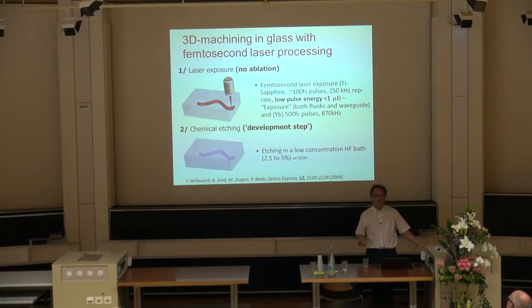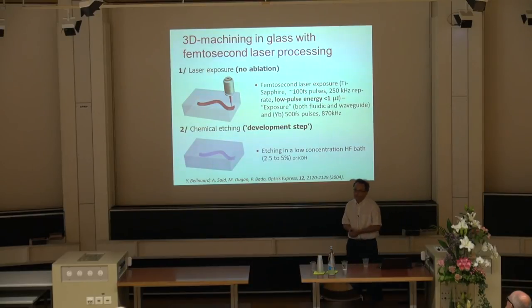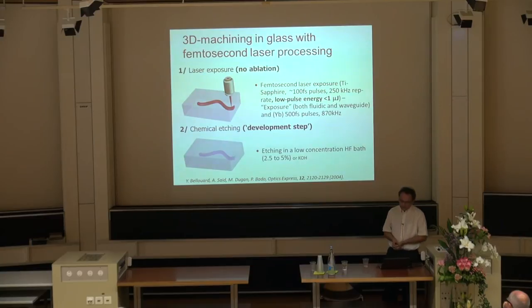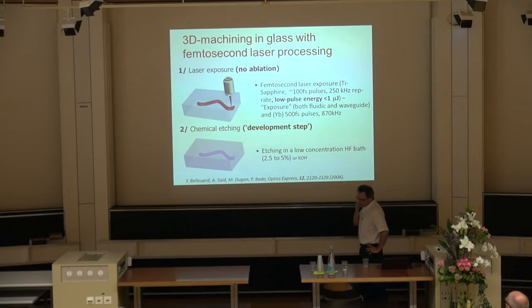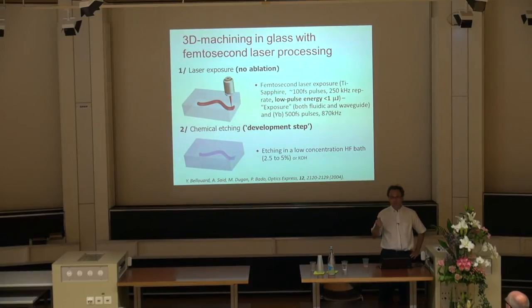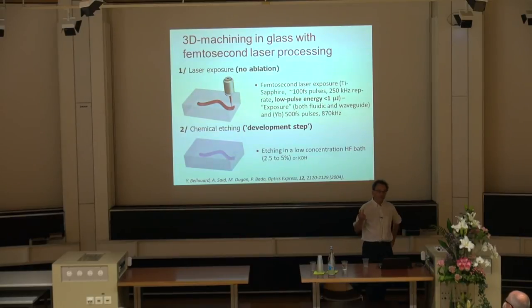Okay, now, how it works. It does sound complicated, but in fact, it's quite simple. We use femtosecond lasers that are actually tabletop. I will show you at the end a picture of the lab, so you will have an idea of how big that is. And what we first do is expose the glass within the volume to the laser beam. And this is done without ablation, so nothing is removed from the material. Okay, that's a very important point. We never remove anything. We just modify it.